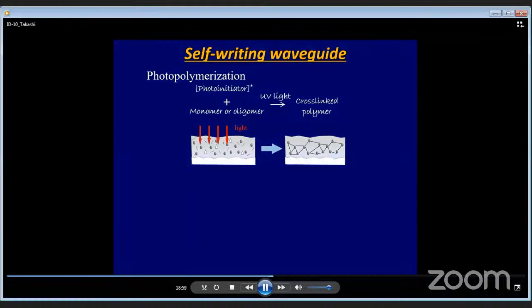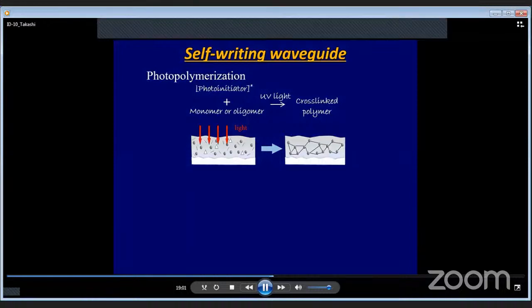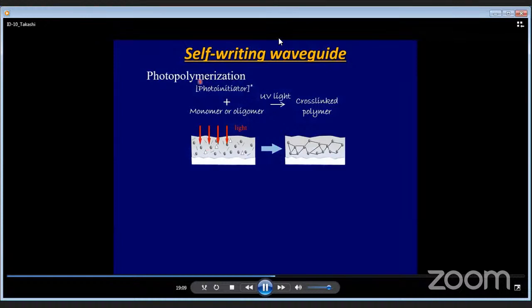The key issue must be the photopolymerization effect by irradiation of UV light or visible light. At that moment, the photoinitiator becomes activated. The activated photoinitiator attacks monomer and oligomer to encourage cross-linked polymerization inside the core region, the liquid phase core region. By using this effect, we can fabricate fiber.